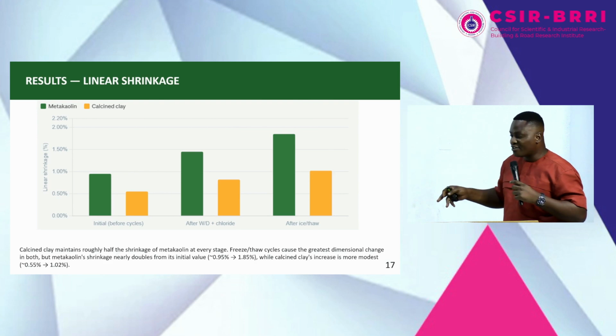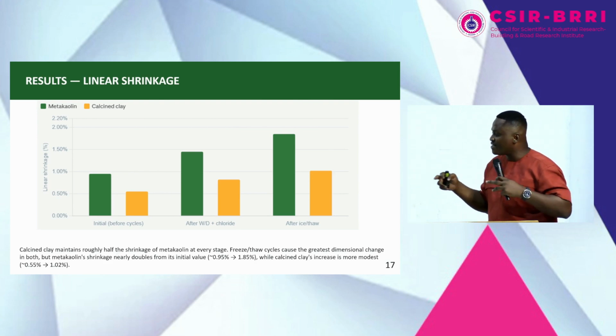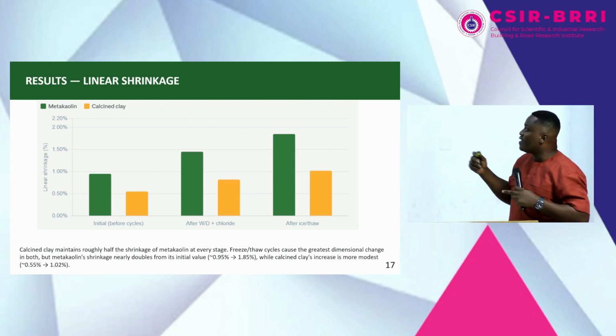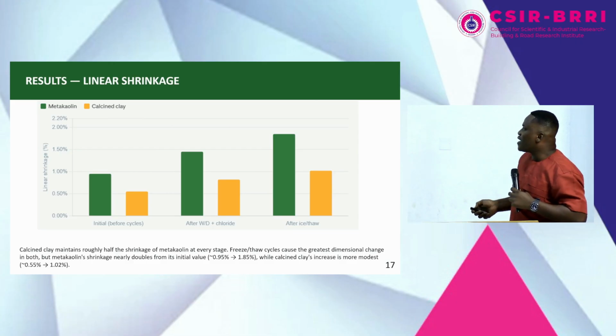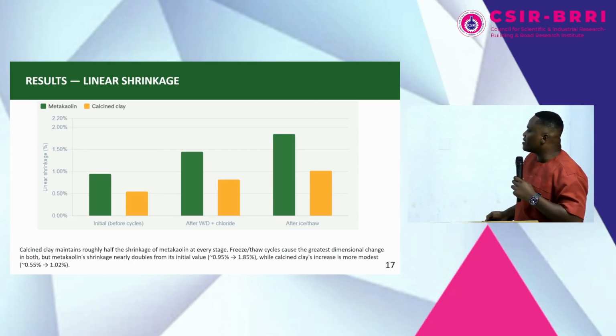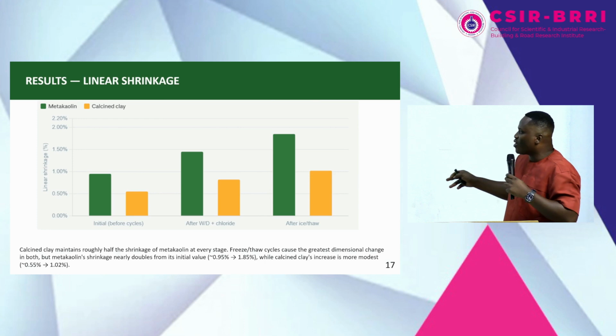And this is the linear shrinkage. So we are looking at just three parameters: the sodium chloride environment, the freeze and thaw, and the shrinkage. And so similarly, the calcined clay is performing better in terms of shrinkage than the metakaolin. The metakaolin is between 0.95% to 1.85%, whereas the calcined clay is 0.55 to 1.02%.